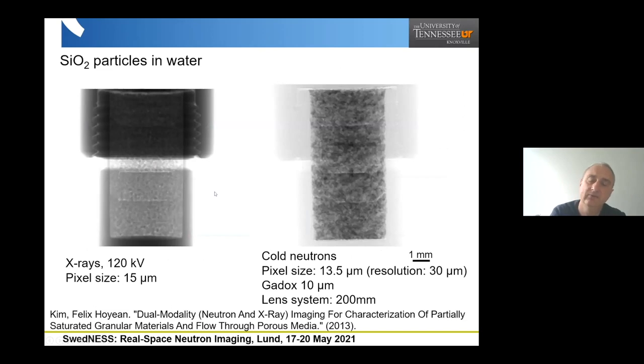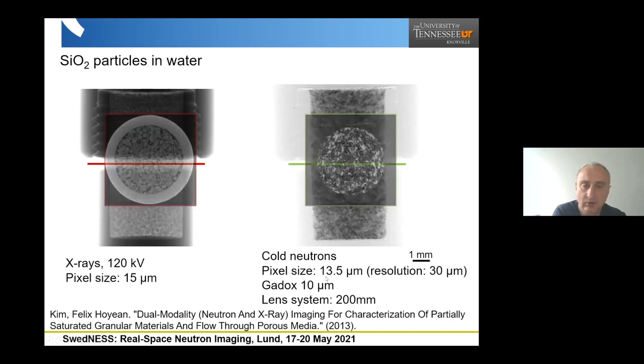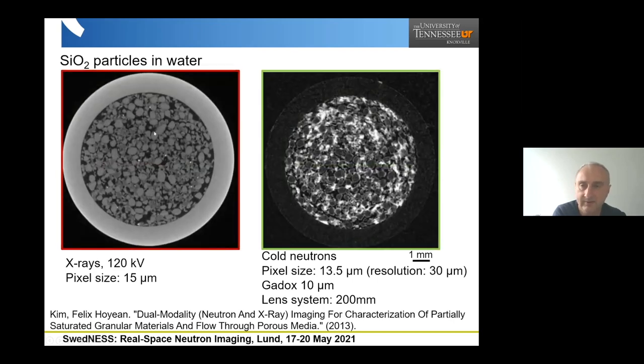So here you see, for example, the X-ray and neutron image of sand with water, or this is a different sand which was compacted. And it was interesting to see how the water distribution looks in different stages of compaction. The pixel size was similar for the X-rays and the neutrons, and performing tomography, we can see the complementary contrast: X-rays are seeing the silicon dioxide or the sand grains, and the neutrons see very well the water between the sand.